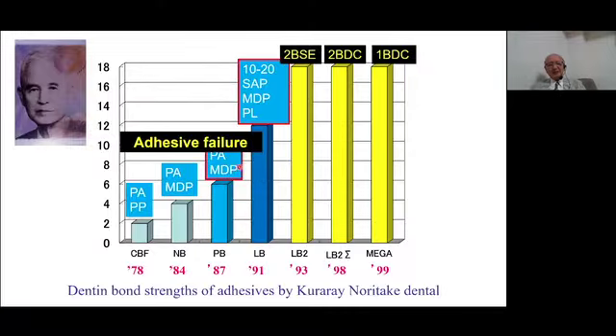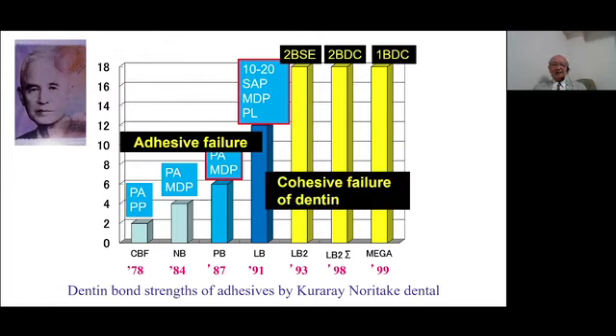However, these materials show adhesive failure when we test the bond strength. Adhesive failure is the debonding between the composite resin and tooth surface. This is debonding. We say adhesive failure. However, in these materials, that is the self-etching material, all the specimens show cohesive failure of dentin. Dentin is broken. The debonding is not seen in the bonding specimens. So, the bond strength of this material is very high.